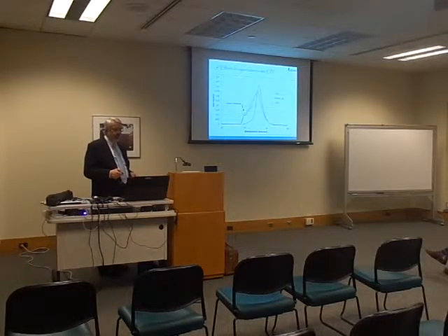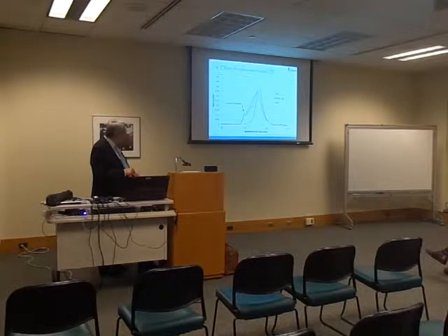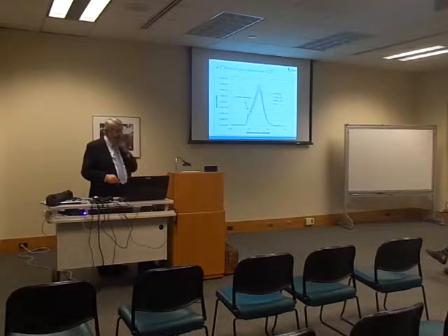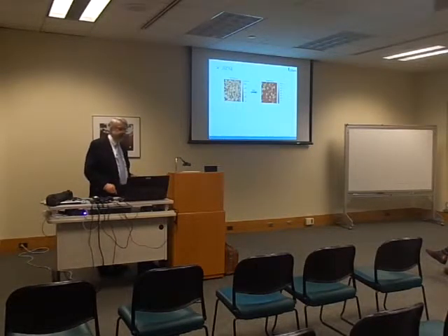When we mixed it, this was our rejuvenator distribution, not very large molecules in this area. The green was the distribution of the aged bitumen with large molecules. For the particular combination, the purple line is the reduction. You see, this area dropped, but also the whole curve has moved in the direction of the small molecules. And the same for others.